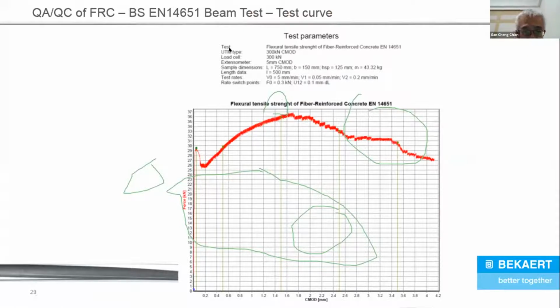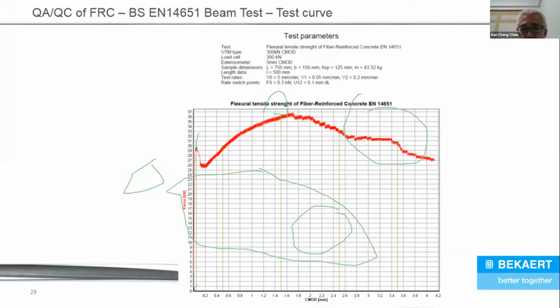And then over here, this point here, this is the LOP. This is the point whereby the first crack of the fiber concrete occurs. And you can see that the point where the first crack occurs is actually around 0.05 millimeter crack mouth. So it's very, very small. So you need to capture this point. Otherwise, if you don't capture this point, then the points behind at 0.5, at 1.5, at 2.5, and at 3.5 will be wrongly obtained. And when it's wrongly obtained, then you will get wrong results. That means this curve could be way below, and it's not at this level.